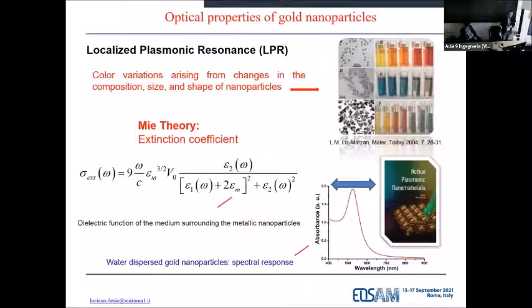Gold nanoparticles, also named plasmonic nanoparticles, have the unique capability to squeeze down a huge electromagnetic field at the nanoscale thanks to a physical phenomenon which is called localized plasmonic resonance. In other words, you shine on a visible or near-infrared electromagnetic radiation, this will produce an oscillation of the bulk free electrons, and such a coherent and dipolar oscillation is called localized plasmonic resonance. As a matter of fact, you can change the frequency, the intrinsic coloration of gold nanoparticles by playing with several parameters, such as size, shape, and geometry, and so on.